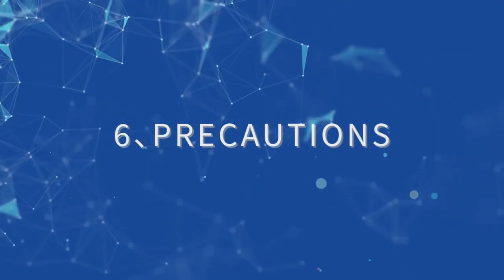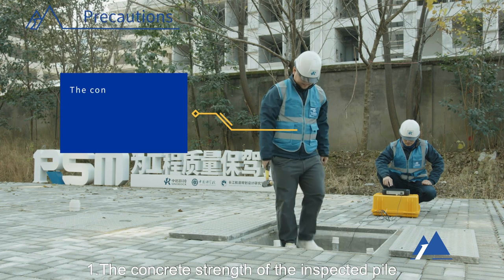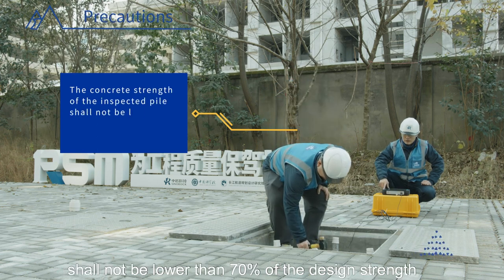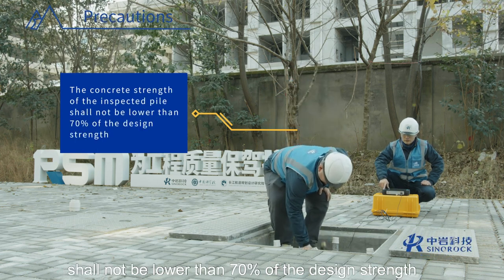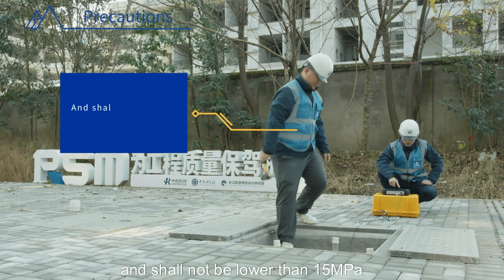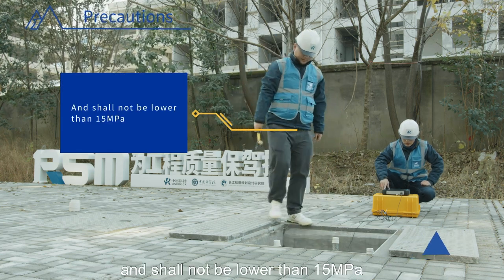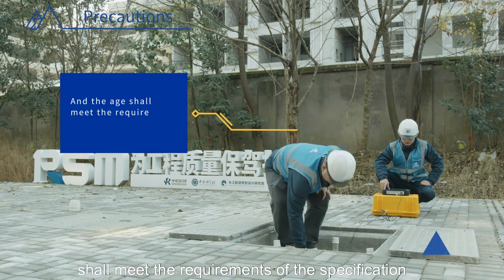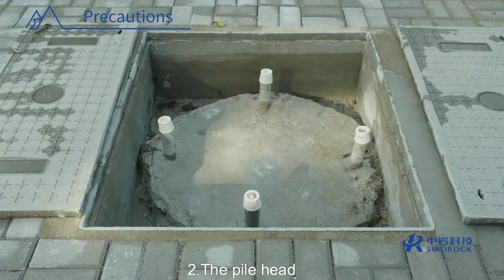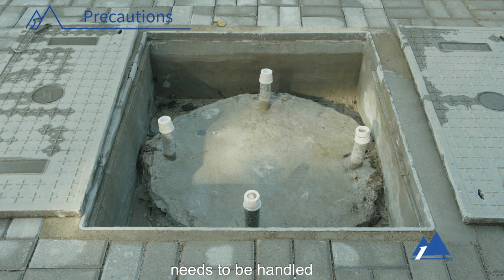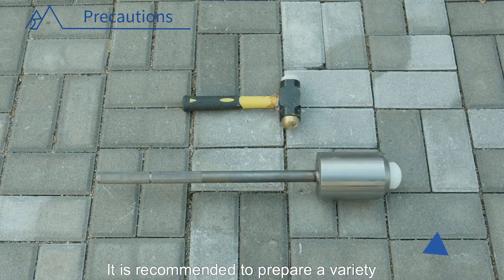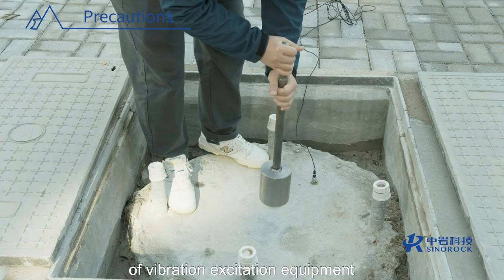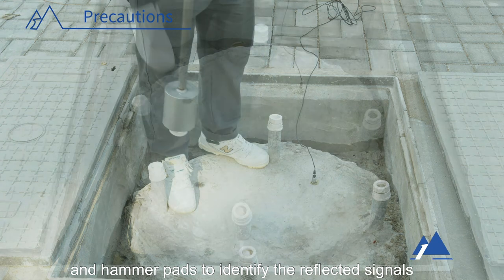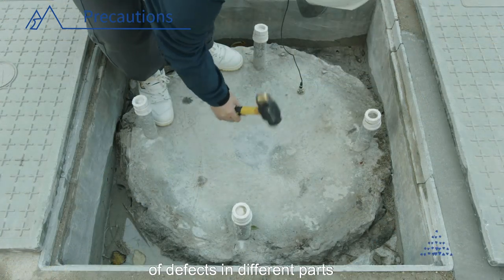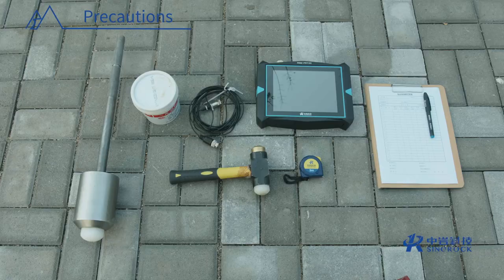6. Precautions. 1. The concrete strength of the inspected pile shall not be lower than 70% of the design strength, and shall not be lower than 15 megapascals, and the age shall meet the requirements of the specification. 2. The pile head needs to be handled in strict accordance with the specifications. It is recommended to prepare a variety of vibration excitation equipment and hammer pads to identify the reflected signal of defects in different parts.